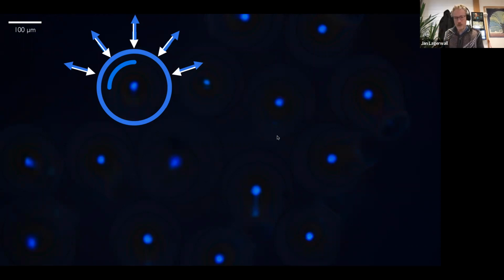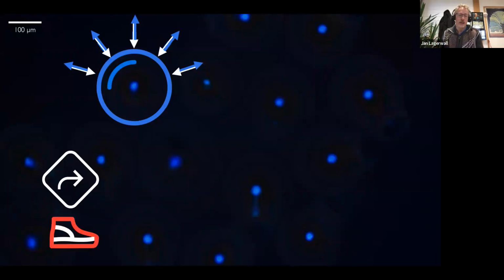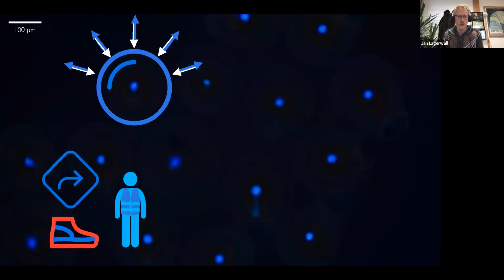And this is something that is really useful, and you can understand that because we already have a lot of retroreflectors in our society. Traffic signs are typically retroreflectors. A lot of fancy clothing are retroreflectors. We have these safety vests in our car, for instance, that are retroreflectors. But standard retroreflectors reflect all light, so that they should be visible, right? So they reflect white light, any wavelength. So they're very bright. If you do retroreflectors with cholesteric liquid crystals, you can tune so that only blue, for instance, is retroreflected, or only red is retroreflected, or the most interesting, only infrared or only ultraviolet.